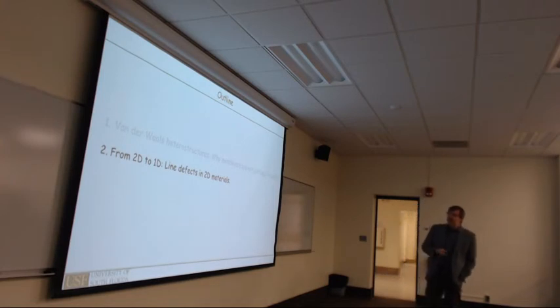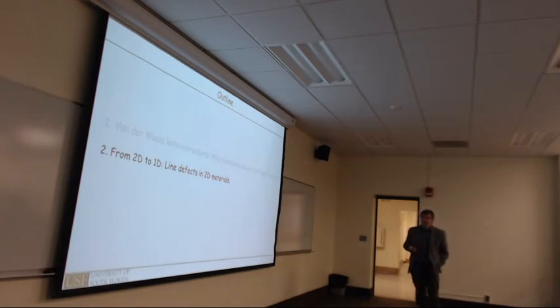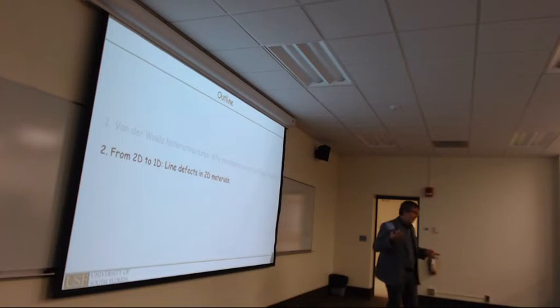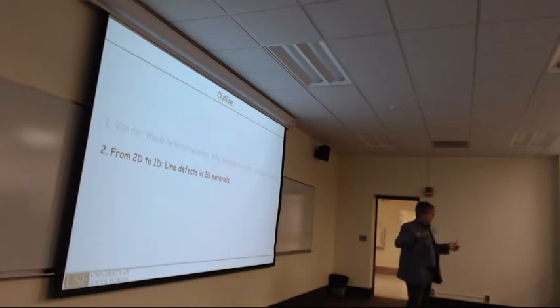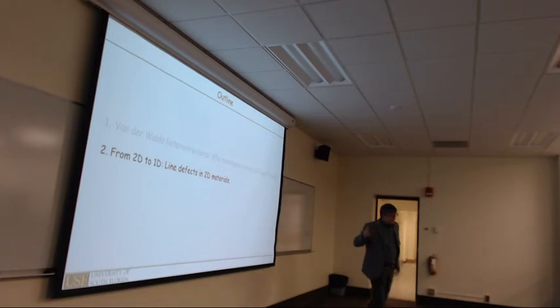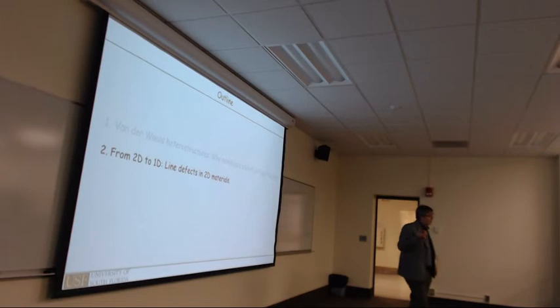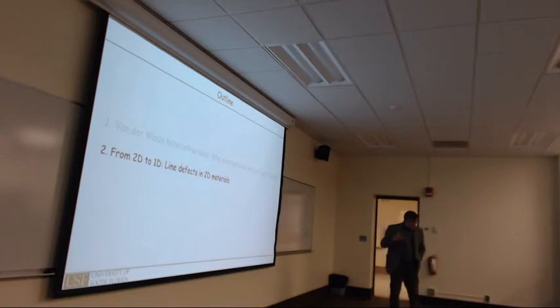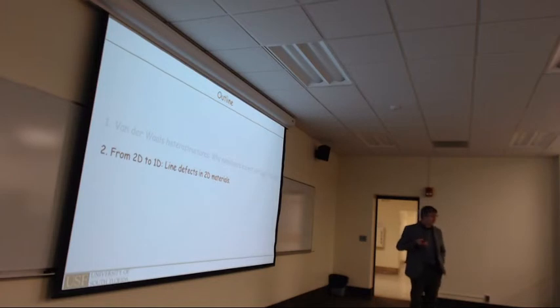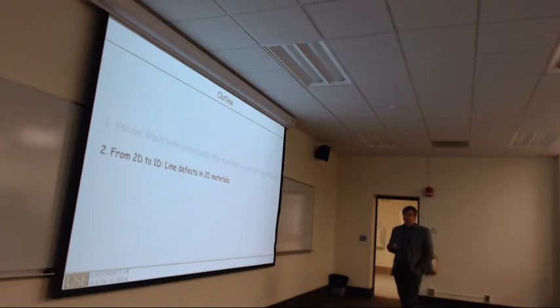So second part, I want to talk about one-dimensional defects, if you want, in two-dimensional materials. So one thing which may not be recognized widely, or maybe it's too obvious, is that if you have a two-dimensional sheet and you induce an edge or a grain boundary, those defects become really one-dimensional materials. And if you have a truly one-dimensional material, it has very different physical properties from two-dimensional materials. If you have electrons confined in a one-dimensional metal, then you would expect very different properties like Tomonaga-Luttinger liquid behavior and strongly correlated effects that you don't have in two dimensions or three dimensions.